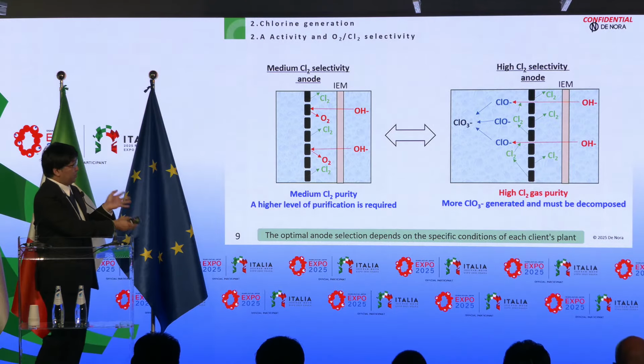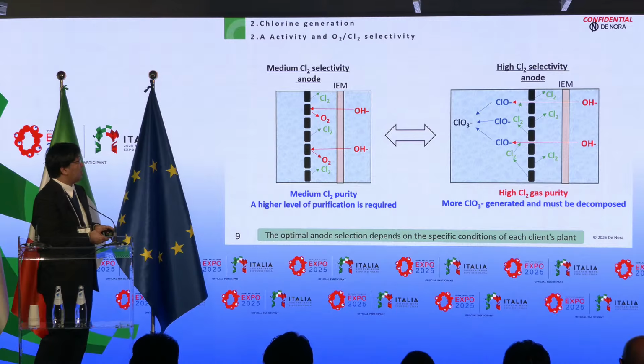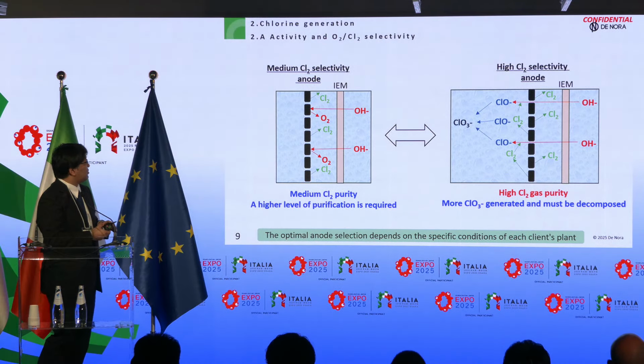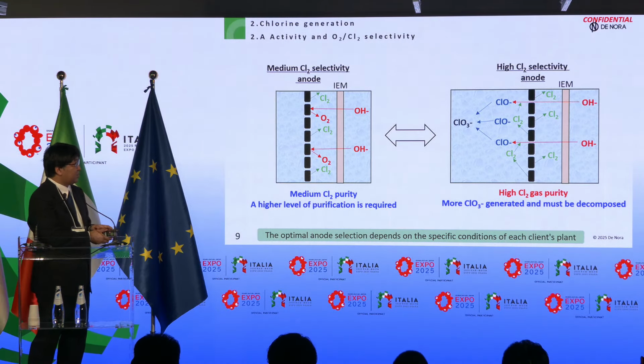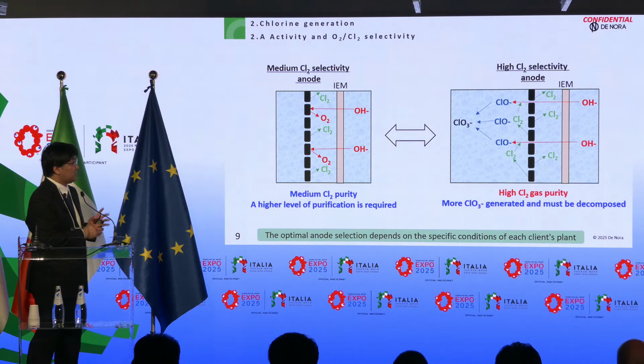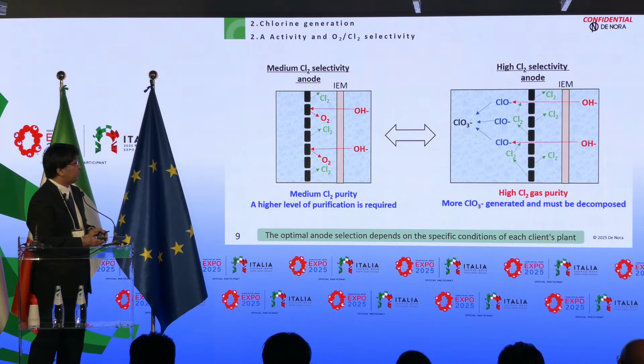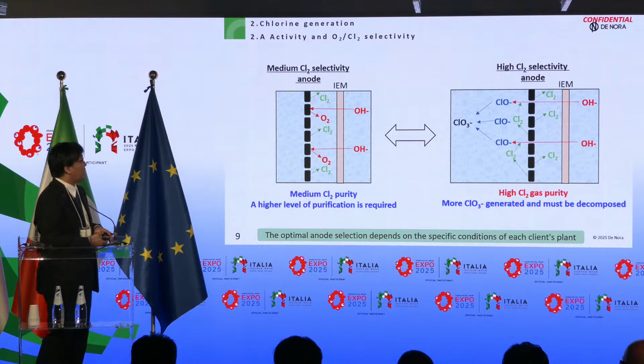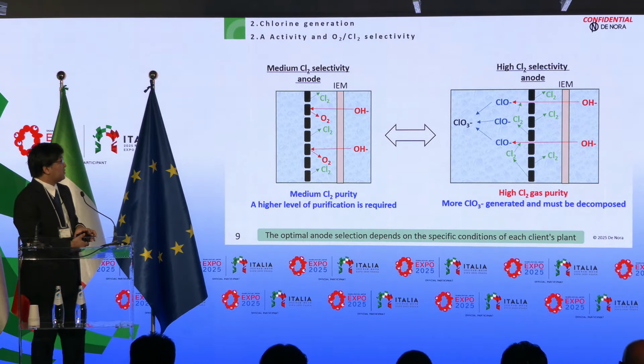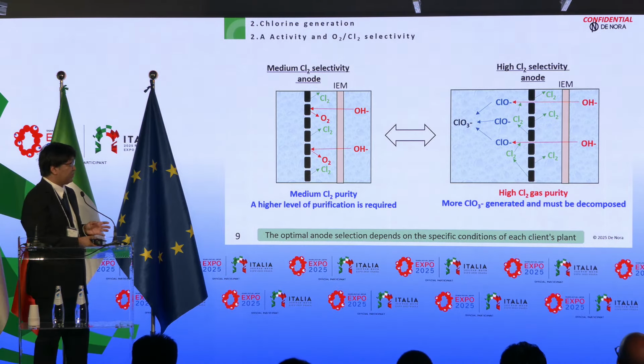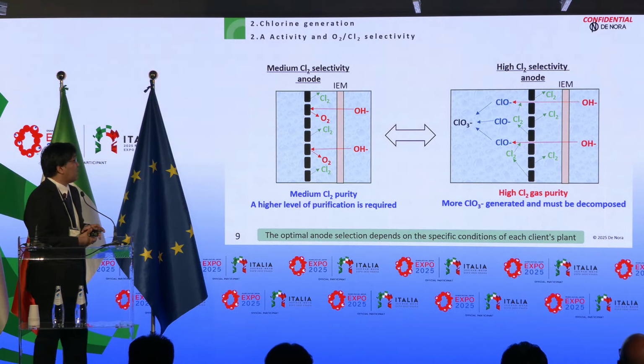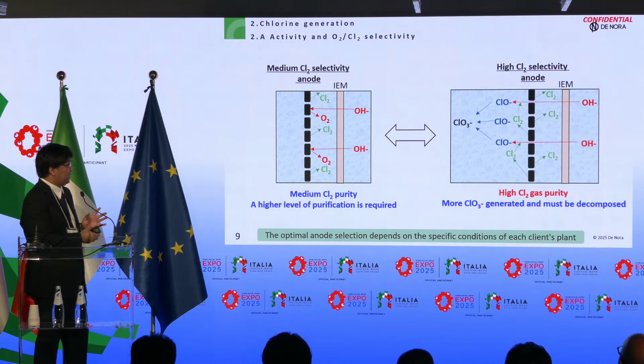In contrast, in the case of a very high chlorine selectivity anode, it generates chlorine selectively. So hydroxide ion from the cathode is not consumed by oxygen generation and reacts with chlorine and generates hypochlorite, and finally it becomes chlorate, which is very difficult to decompose. Decomposition of chlorate requires a lot of hydrochloric acid, so too much chlorate generation leads to higher operating cost.